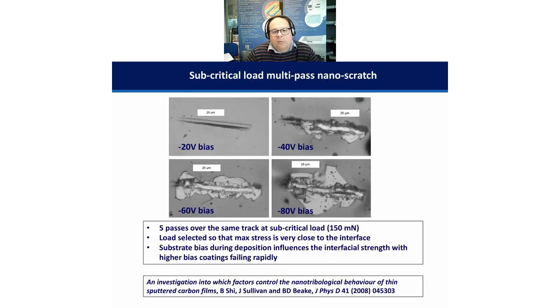So this is a multiple pass wear test, and this is quite nice. It shows a comparison of 4 different samples. These samples are similar to one another in the sense that they are the same coating material on the same substrate, but they're different in the sense that the bias which is applied to the substrate during the deposition process is different. So here you've got minus 20 volts bias applied, and here minus 80, and various levels in between.